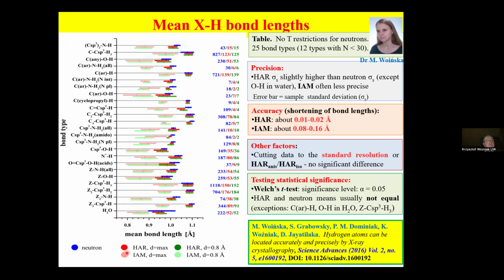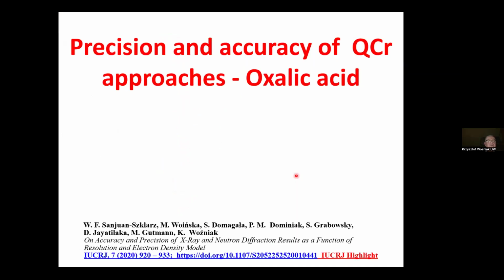the resulting distribution of the same bonds obtained from HAR for maximal resolution, and deep green for resolution cut to 0.8 angstrom. And this light red color and light green are showing independent atom model refinement. So no doubt that Hirshfeld atom refinement for all possible types of bonds to hydrogen atoms is giving almost neutron quality bonds and far better than independent atom model. So that is showing the importance of HAR when hydrogen atom is involved in the problem.